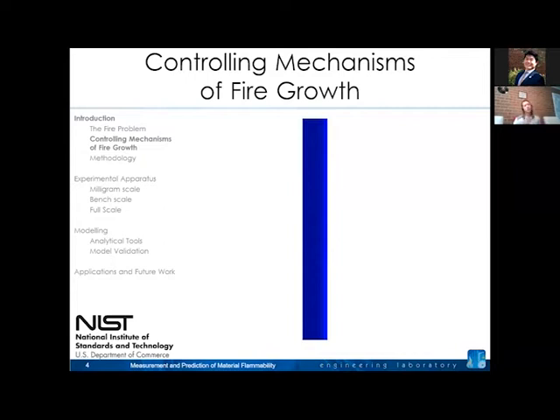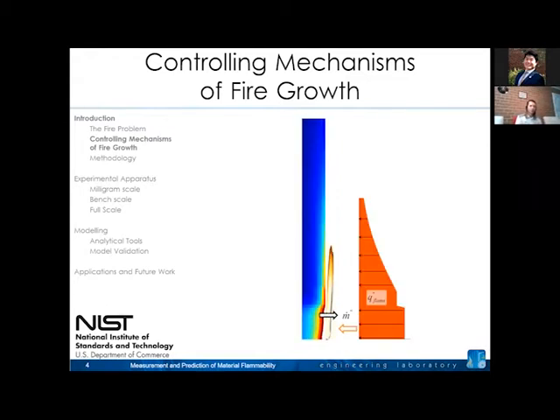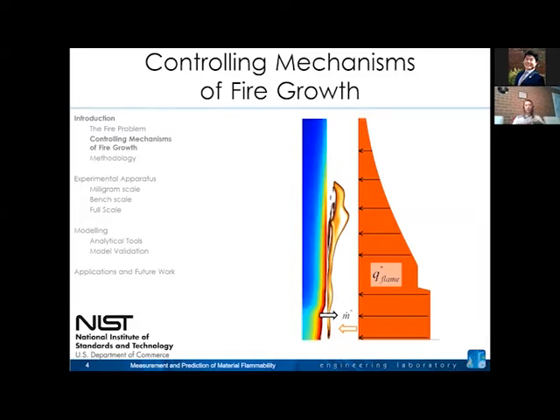A very broad overview of how things burn: imagine a combustible solid heated at its base. As it heats up, it degrades and produces flammable vapors that go to the gas phase, burn with the ambient oxidizer, and release energy — some of which feeds back into the material itself. This causes further heating, more material degradation, more fuel to burn, and fire growth. This is a positive feedback loop between gas phase energy release and solid phase material degradation. The burning rate is our key predictive quantity. We call solid phase degradation pyrolysis and the gas phase process combustion.